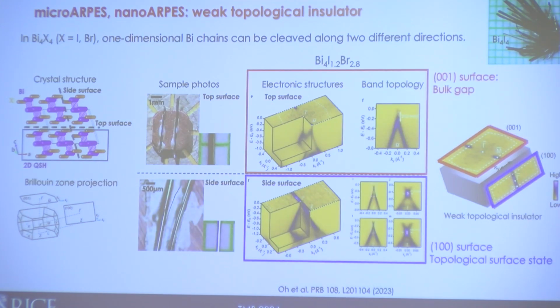Just to make a point, with these micro-ARPES and nano-ARPES techniques, you can actually cleave on different surfaces and look directly at the electronic surface states on the 001 surface, which is shown here on the top. We can see that there are no topological surface states. This is just a bulk gap, which is close to the Fermi level. But on the side surface, you can mount the sample sideways. This is like a 50 micron size surface, which we can measure directly, and we see two topological surface states. And this is a direct way to see that this is a weak TI instead of a strong TI. So this is an example of the type of things that are now enabled by micro- and nano-ARPES, and many others.